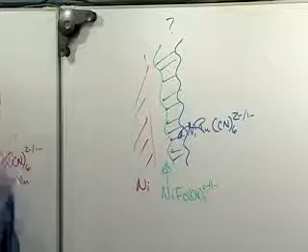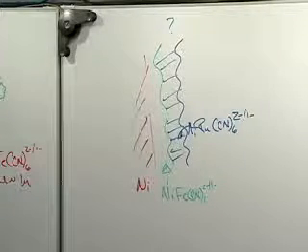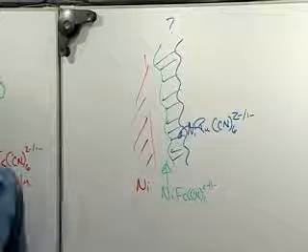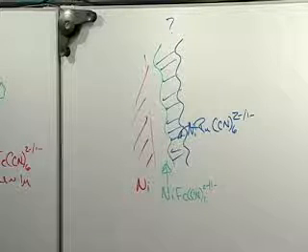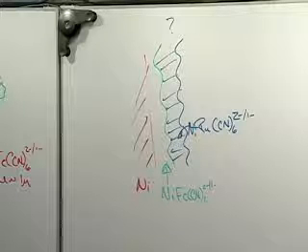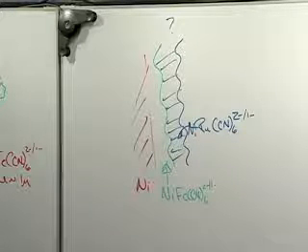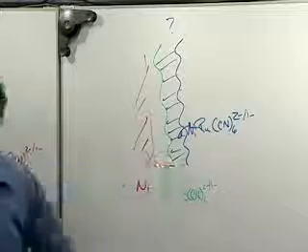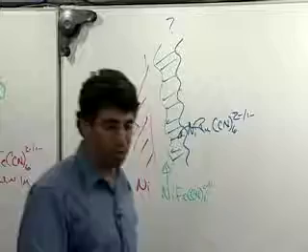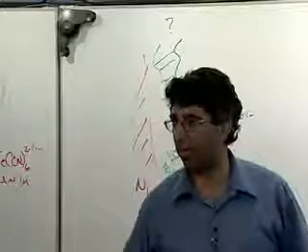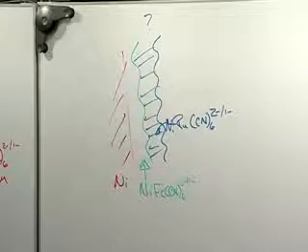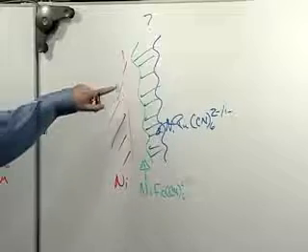It's pretty surprising you can see that. Where does the nickel come from? From the electrode. Yeah, there was enough nickel. We know how to corrode nickel electrodes well. We can always get them to diffuse through the nickel ferricyanide, to make this layer in this model. How thick is the first layer? Well, we'd have to integrate that, but it's approximately 100 angstroms thick. So it isn't the nickel diffusing through, though, but rather the nickel in the ferricyanide. It could be that, right, that there are nickels in this ferricyanide layer, so maybe it's just grabbing those or something.